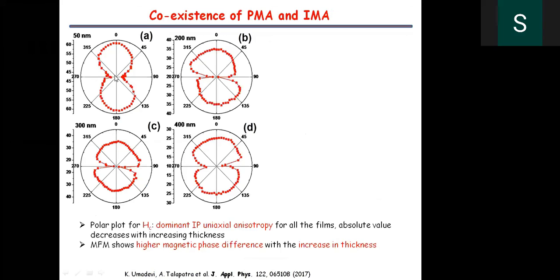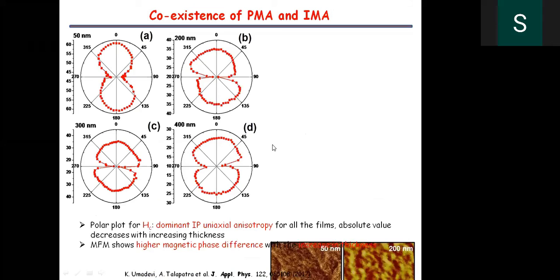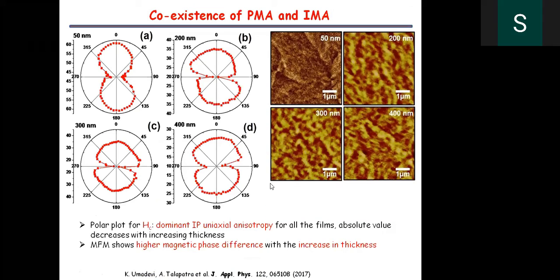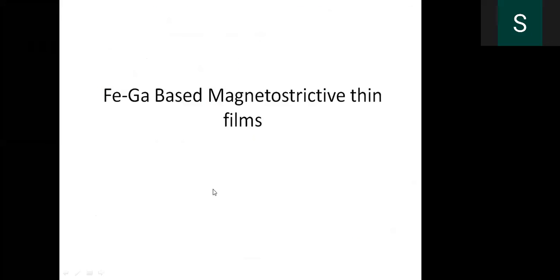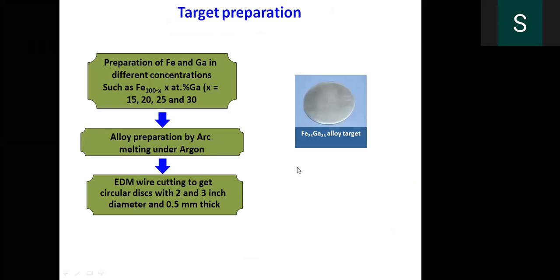This essentially shows the easy and hard direction. The direction along which the coercivity is maximum is the easy direction, and the perpendicular direction is the hard direction. This has been complemented with vibrating sample magnetometer measurements. The out-of-plane anisotropy is also measured with magnetic force microscope images. Although these rare earth materials showed out-of-plane magnetic anisotropy, the magnetostrictions are very low. So we have gone for developing the same iron gallium based material in thin film form also.